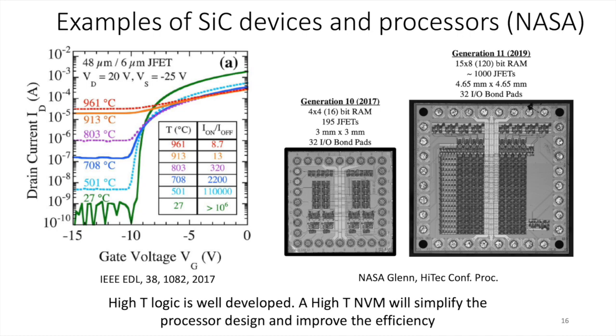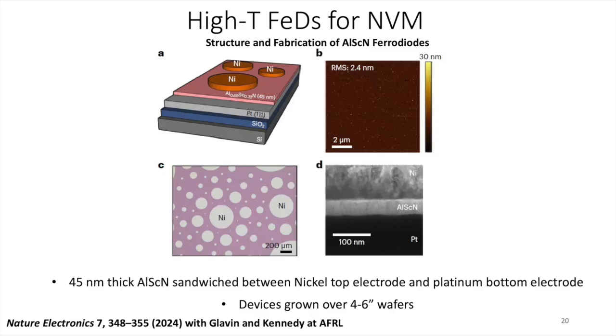If you go to slide 20, these are the prototypical devices that we have made and demonstrated. These are again made from aluminum scandium nitride material, as you may expect, because of its very high and very stable ferroelectricity at high temperatures. The device is actually very, very simple. It is a sandwich between nickel electrodes, platinum electrodes, and aluminum scandium nitride. It's a 45 nanometer thick film in between.